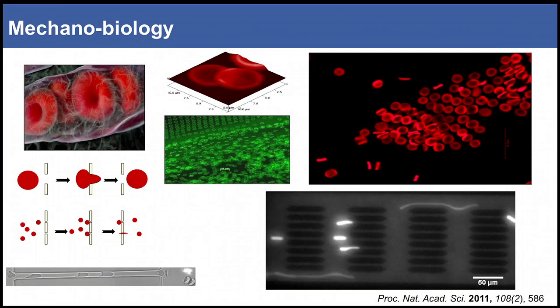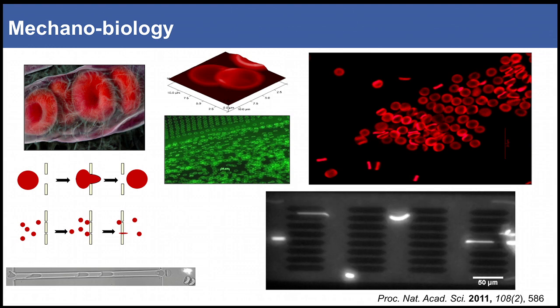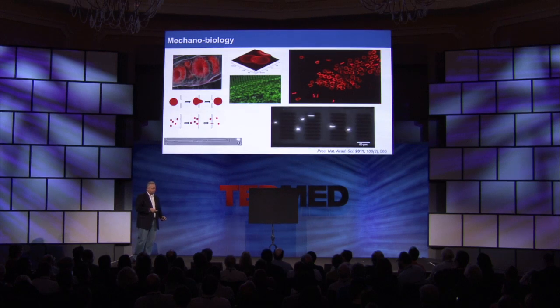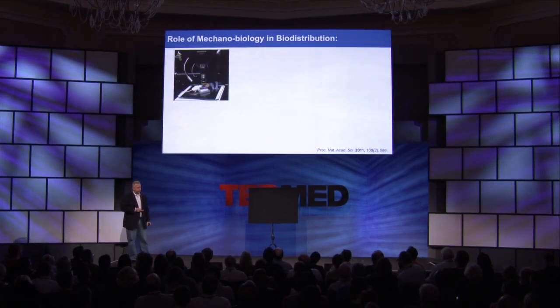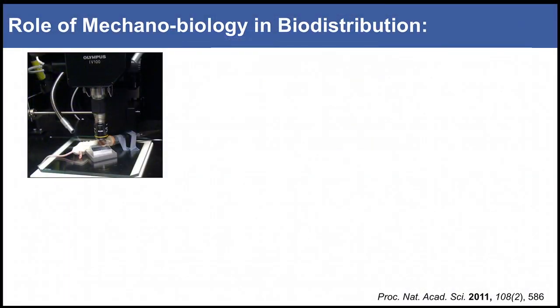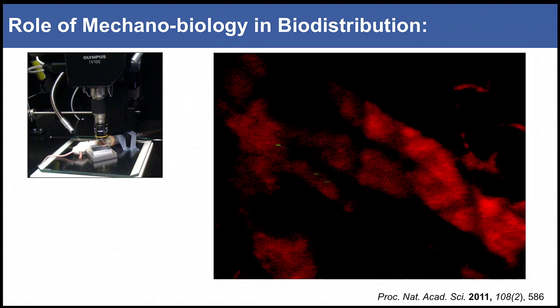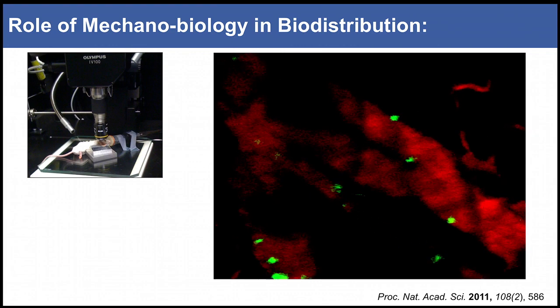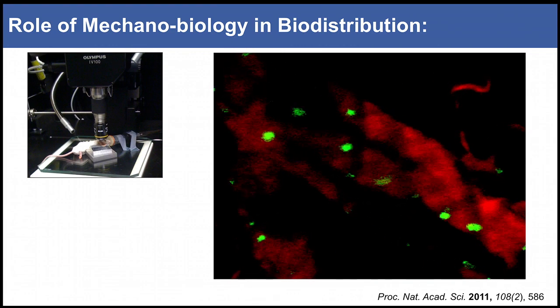We've been able to mimic and fabricate hydrogels that have the same size and shape as real red blood cells, and we can systematically vary their elasticity so that these particles can flow through gates in a microfluidic channel that mimic the barriers in our bodies. Once we match the modulus of a real red blood cell, we can begin going in vivo. Using an intravital microscope sitting on the earlobe of a mouse, we inject our particles and look at capillaries in the ear — and these become long-circulating particles. Matching size, shape, and elasticity gives us particles that circulate for a long time.